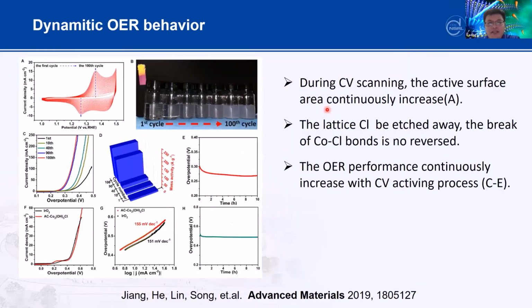And interestingly, during the OER behavior, we found something very interesting: during CV scanning, the active surface area continuously increased. If you look from the first cycle to the 100th cycle, the solution color even changes, right? As you can see, the catalytic activity continuously becomes better and better.